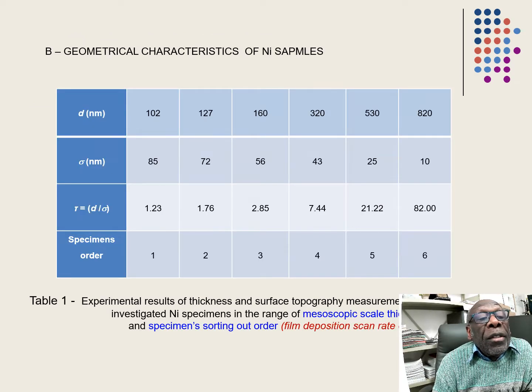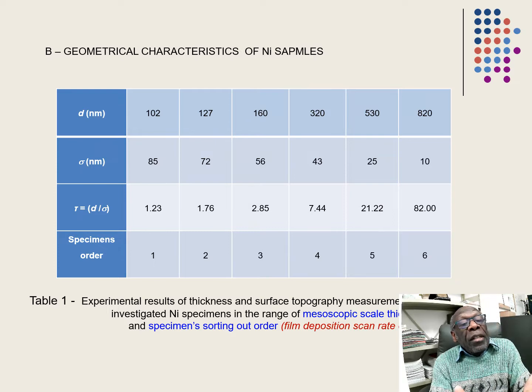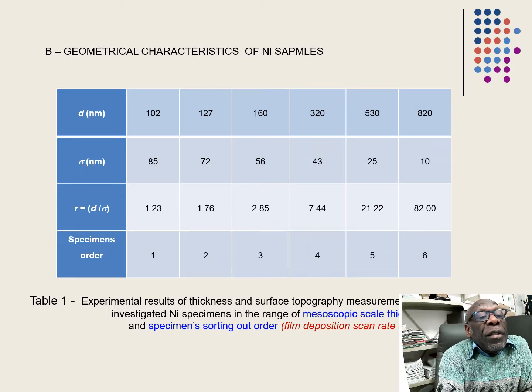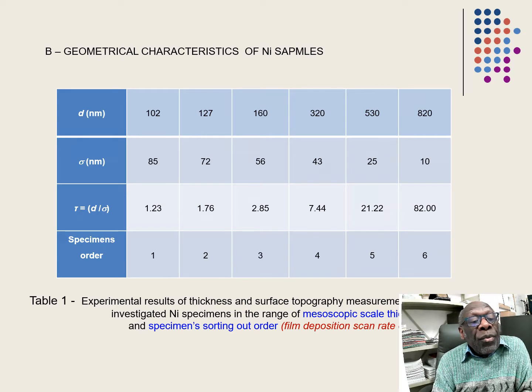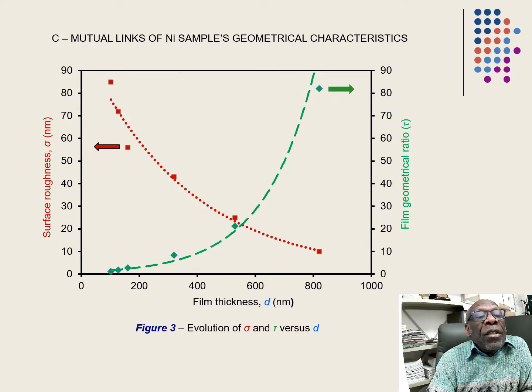The results obtained with all the investigated samples are given here. You can see that we can order the investigated samples using D value and tau, and here we have the same evolution of the samples. The order is the same using D or using tau. This is a coincidence, because it's not always obligatory to have the same evolution. Here, the link between the different geometrical characteristics, decrease and increase of each one of them versus film thickness.